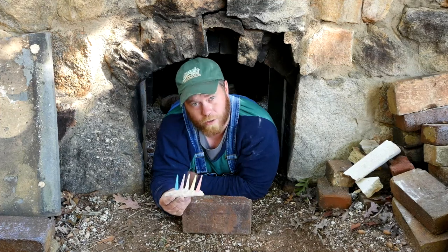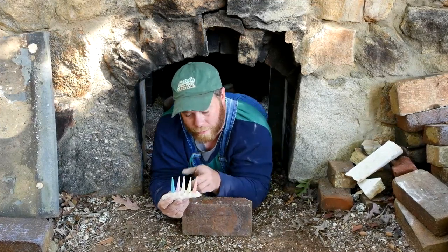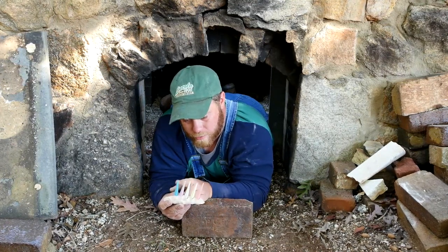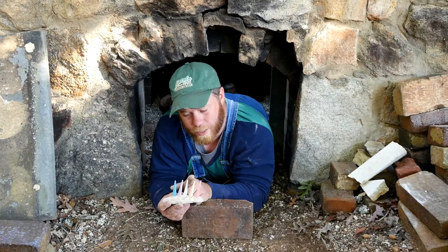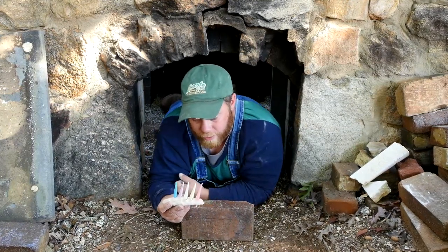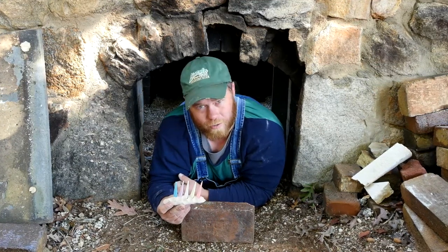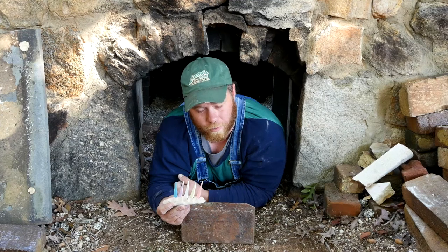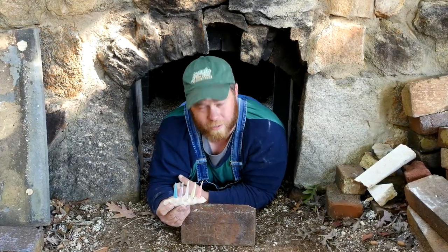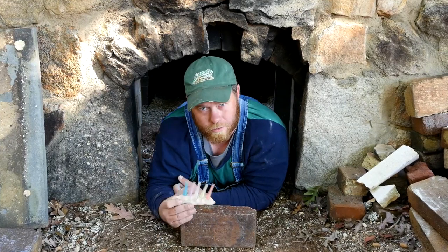What they do is, after a certain amount of heat work, which is a combination of temperature and time, they begin to bend and they'll fall over one at a time, starting with this one and ending with this one. When we get this pyrometric cone just about halfway laid over, we'll be just about done and we can stop firing the kiln. And there again, it's just a way to help us add just a little bit of modern technology without going too far from an old tradition. We still look at the soot line, we still look at the flame, and look at the color in the kiln, but this is just a little extra insurance.